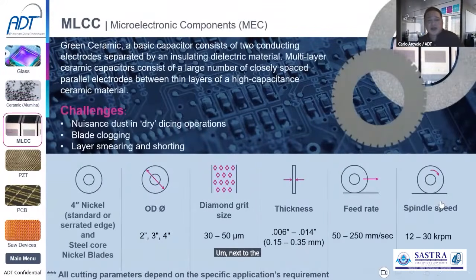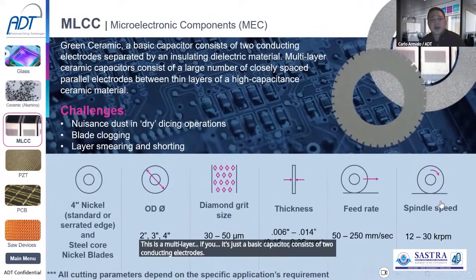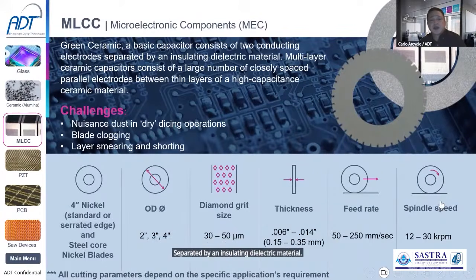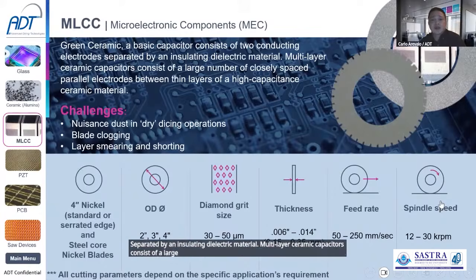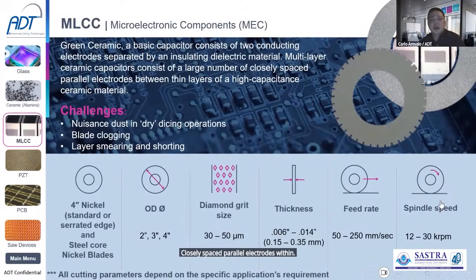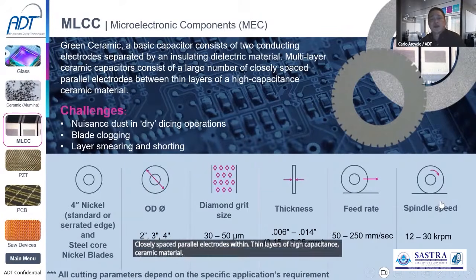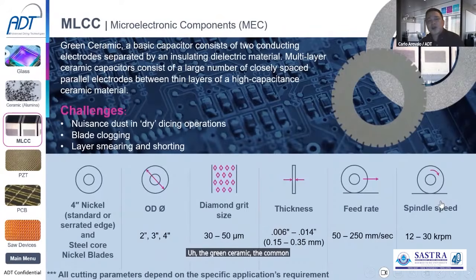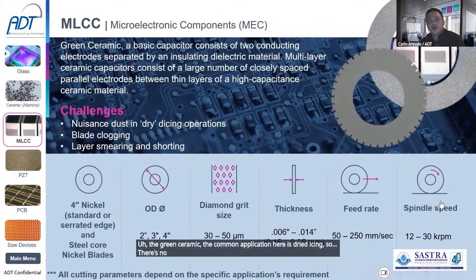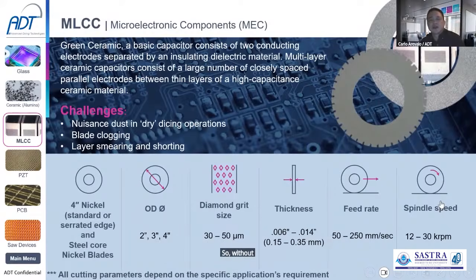Next to the MEC application is MLCC, or what they call the green ceramic, this is a multi-layer ceramic capacitor. It's just a basic capacitor, consisting of two conducting electrodes separated by an insulating dielectric material. Multi-layer ceramic capacitors consist of a large number of closely spaced parallel electrodes within thin layers of high capacitance ceramic material. For the green ceramic, the common application here is dry dicing. So there's no coolant, there's no water that's being used during the dicing process. Without this water or coolant, you're dealing with a lot of dicing dust or material dust during the dicing process. So this is causing a lot of issues.